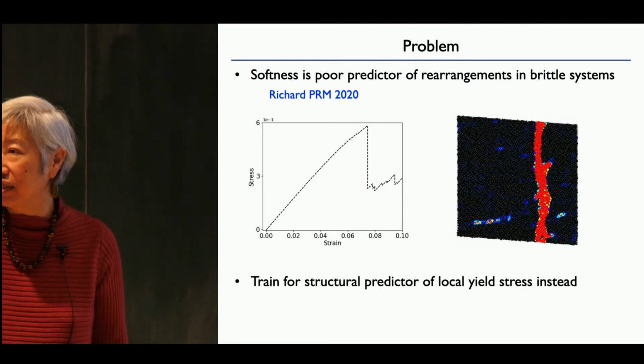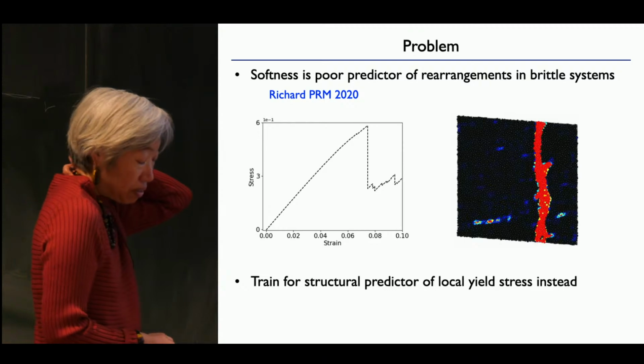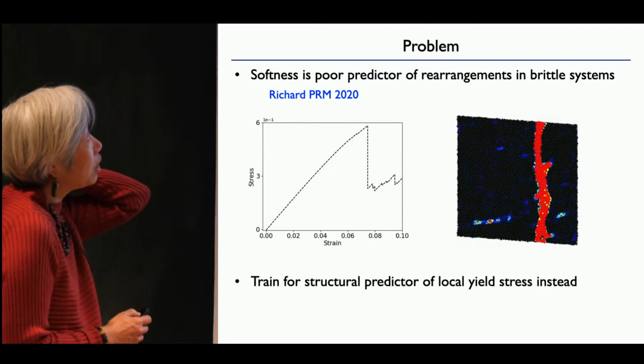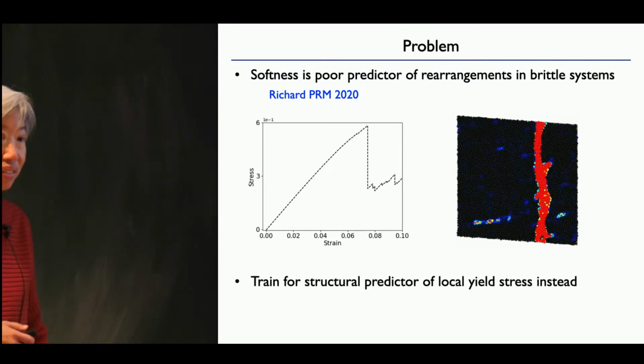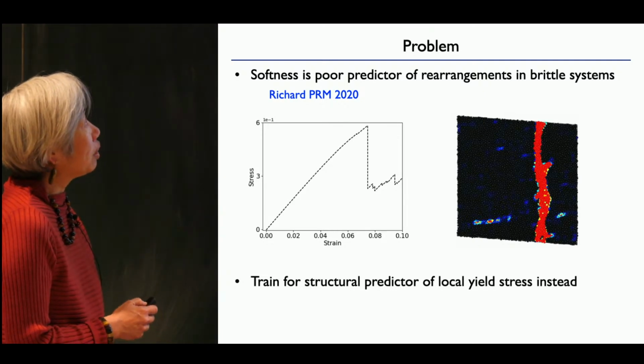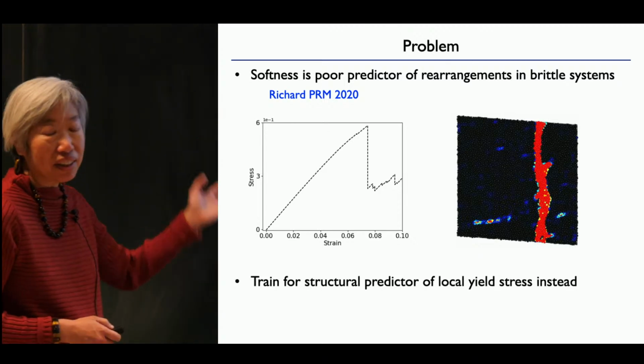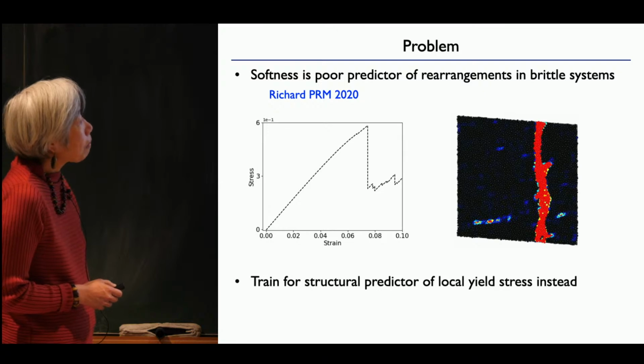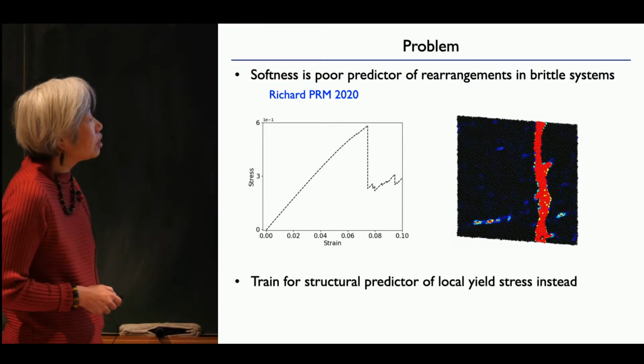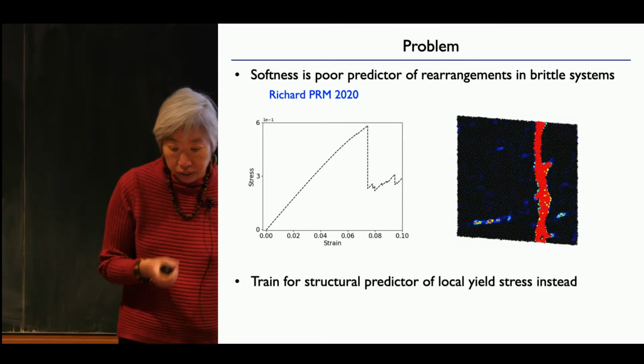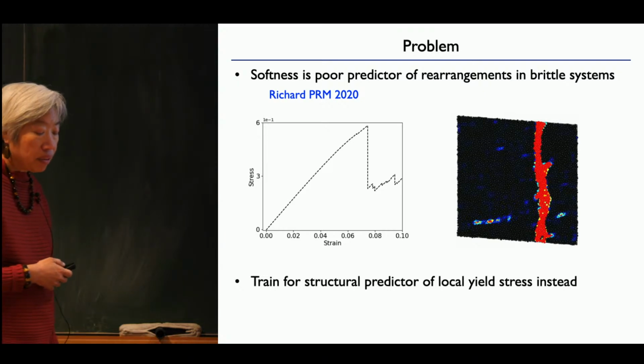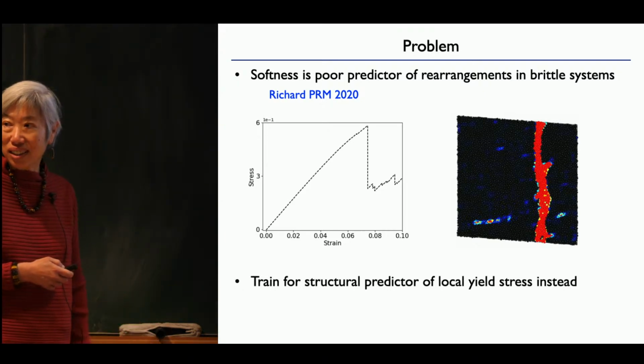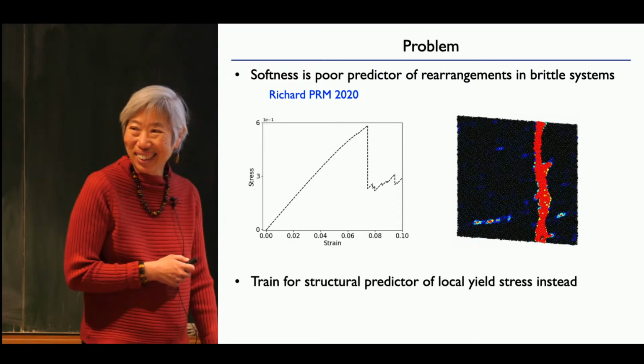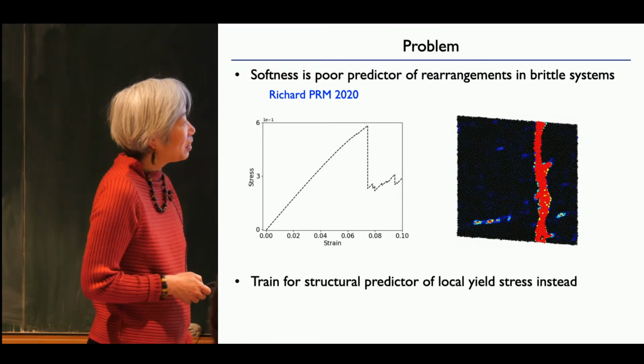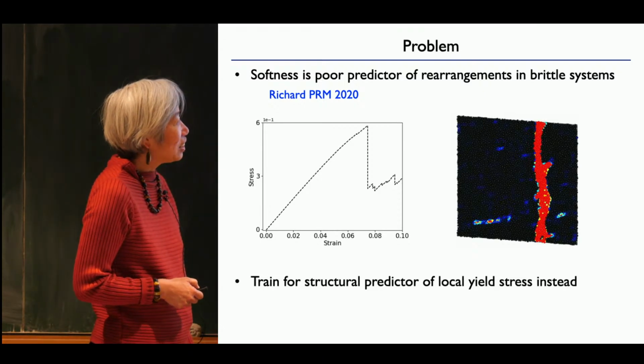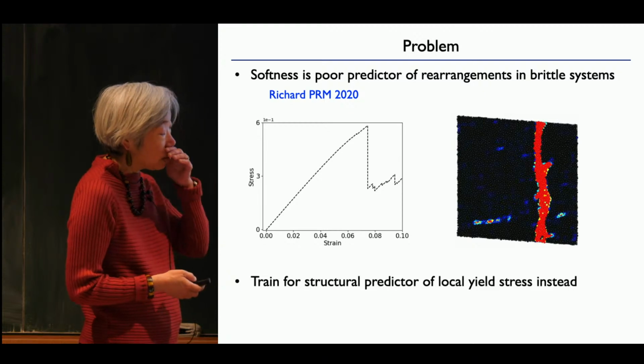But the problem is that softness, it turns out, is an extremely poor predictor of rearrangements in brittle systems. That was shown in this paper that David mentioned yesterday, which he pulled together as an amazing feat, where he compared many different predictors of rearrangements. So instead of training on D squared min, what we ended up training on was the local yield stress. The local yield stress does turn out to be an excellent predictor. There's David. Your heroic effort in pulling this paper together was quite impressive. So the local yield stress is quite a good predictor of rearrangements.